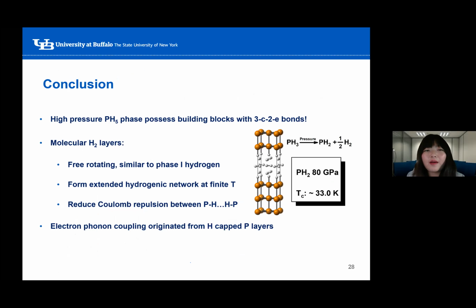So to sum this up, we found a high-pressure PH5 phase that has building blocks resembling 3-center 2-electron bonds. We find structures containing molecular hydrogen layers. They are freely rotating, they can form an extended hydrogenic network at finite temperature, and their role was to reduce the Coulomb repulsions. So for all the structures with Tc, the electron-phonon couplings mainly originate from the hydrogen-capped phosphorus layers, not the H2 layers.